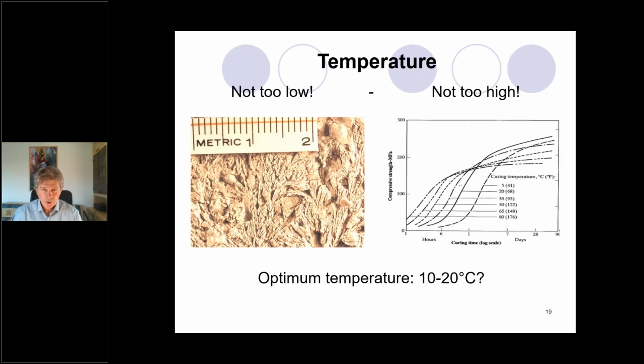Temperature of curing is an extremely important parameter. We cannot cure under too low temperatures. Otherwise, you can see the crystals of ice. Portland cement doesn't react with ice. Even more, below approximately minus 10 degrees, we can neglect the hydration rate. It's almost zero. And not too high, because if you have too high temperatures, we can make some damage to the hydration products. I'm speaking about mature age strengths, not early age strengths.